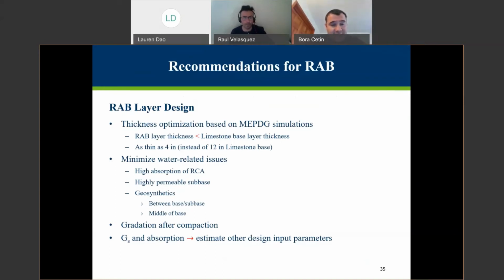One thing that needs to be picked on, again, the high absorption values of RCA need to be checked and limited. And you may want to have a highly permeable sub-base in some of the cases with these RCAs, and maybe use some specific geosynthetics. Again, calcite precipitation may be an issue, so you may want to use some geocomposite design between the sub-base and base layer to minimize that calcite precipitation issue. And again, we talk about the gradation, especially for coarser RCA materials. Gradation after compaction needs to be checked.